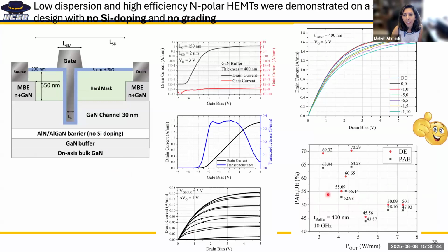And we showed actually, comparable to the other state-of-the-art devices at 10 gigahertz, we got output powers as high as 7.5 watt per millimeter, and efficiencies as high as 70%.